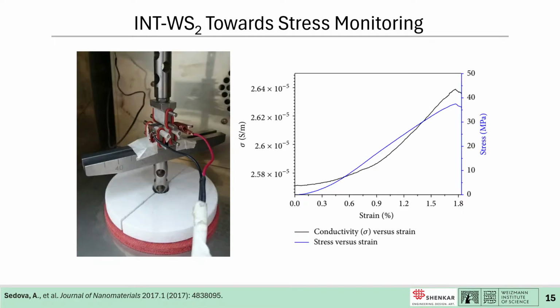And how did we measure it? We basically did a 3-point bending test where we press into the samples until they break, and we measured the conductivity at the same time. And we basically could observe the same thing as Roy Levy observed on single nanotubes, that the electrical conductivity increases with the stress.